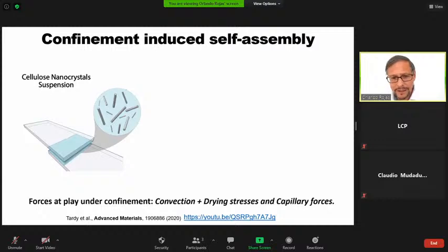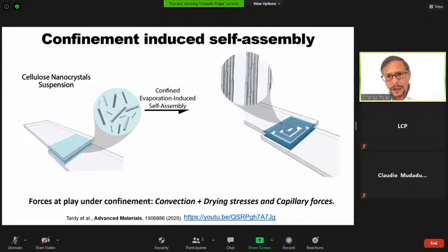But what happened this year, starting with work that we began in 2019, is the simple idea of taking cellulose nanocrystal aqueous suspensions, putting them in between two solid surfaces and letting them dry. In a short time, that material will form an assembly that is quite interesting. And that assembly makes the bonding between the two surfaces quite strong. And that has received a lot of attention in the community, the fact that we have this type of glue. It's a glue that is anisotropic, meaning that it doesn't break in the shear direction, it has extremely high strength in the shear direction.